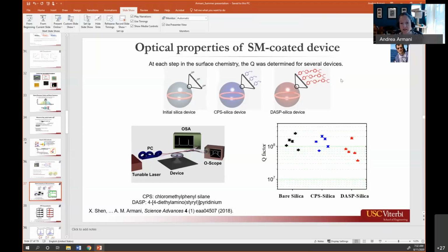Because a lot of surface chemistry processes you can just do in a reaction vial with a magnetic stir bar. But if you put a silicon wafer in a vial with a magnetic stir bar, you end up with silicon powder. And that's not good. We lost a lot of devices that way. We made a lot of powder.